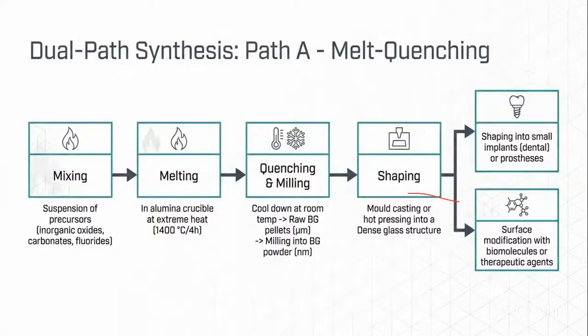And when you look into the melt quench technique, this can be synthesized in two different phases. One is the basic melt quench technique, and once you have quenched it, you don't prepare it only as a glass which is highly transparent. You can also come up with BG powders, bioglass powders. The moment you form the powders, you have to mill them. And then you can mold cast them and check for dental applications. You can also check those bioglass powders for whether they can be used as therapeutic agents or anything of that kind.